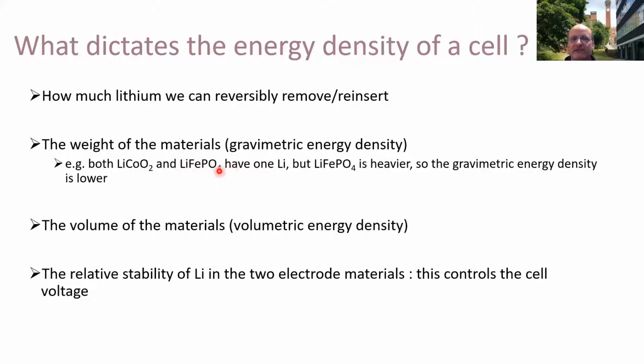It's a much cheaper material because it has iron rather than cobalt. However, it's heavier. If you work out the relative molecular mass of this compared to this one, it has a higher relative molecular mass. Each of them has one lithium. And so the energy density of this one is higher because it's a lighter material. We can, in theory, remove the same amount of lithium, but this lithium cobalt oxide is lighter, and so its energy density is higher.